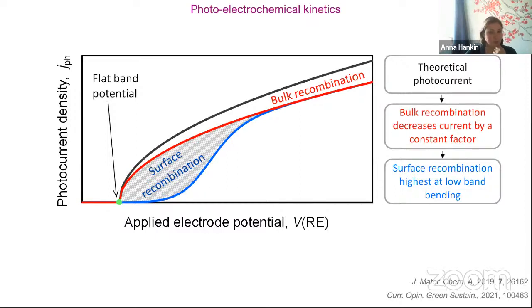And knowing this potential at which zero current would flow is very important for modeling, right? Because the current is something applied relative to something. So it's good to be able to say at this point we expect nothing, and then we expect the current to increase, and we describe mathematically how that should happen. And the determination of this flat band potential has proven to be one of the most difficult things I've ever done in my research.